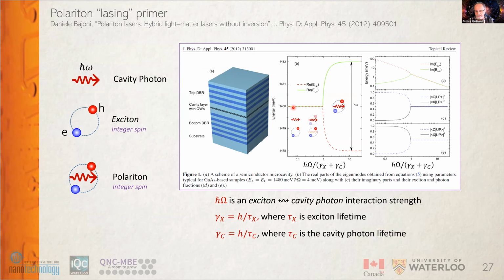But the transition to create them, you can see, this is as a function of strength. So ħΩ is the strength of the interaction between the two. And the gammas are broadenings which are related to the limited lifetime of the photons and the excitons in this cavity. And so this ratio has to be larger than 1. And you can see that looks almost like a phase transition, where from simple perturbation we are going into the so-called strong interaction. So your levels, which initially are degenerate, split up, and this is called Rabi splitting, and you generate the lower and upper polariton branch.